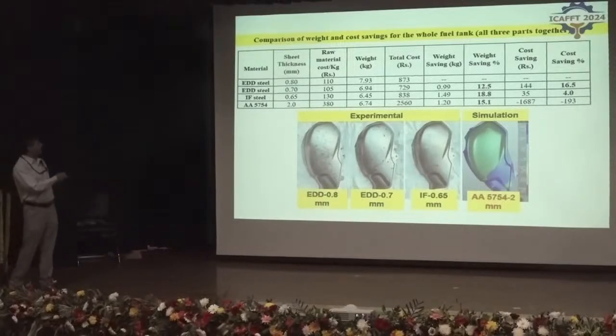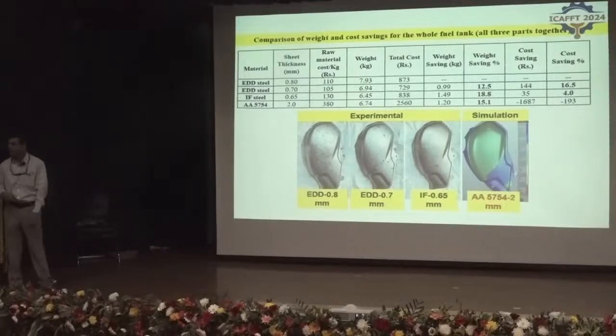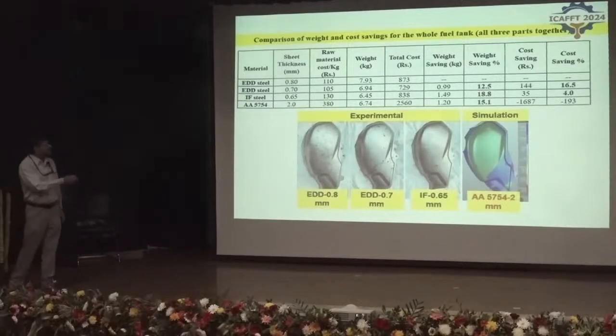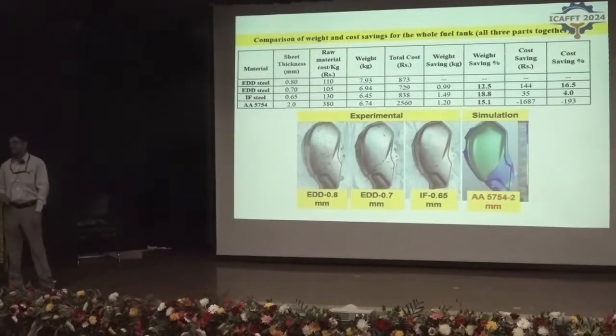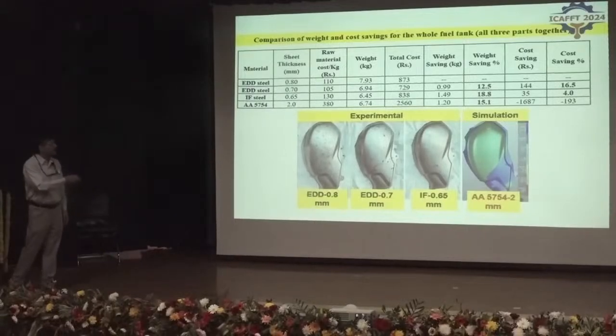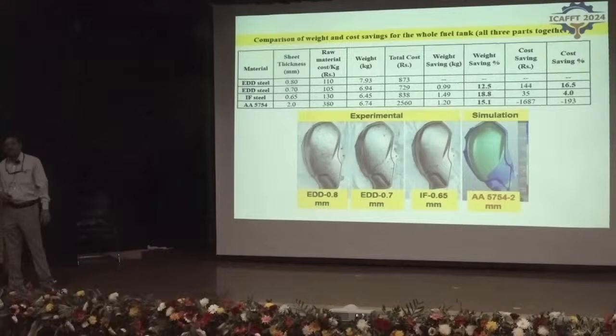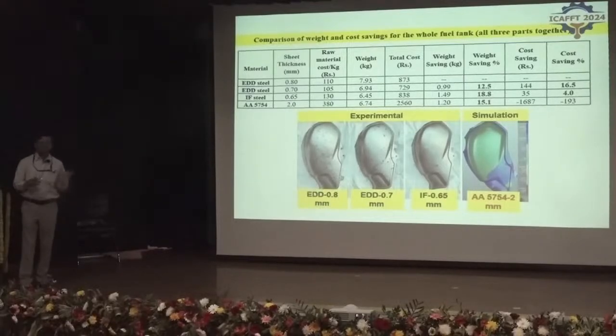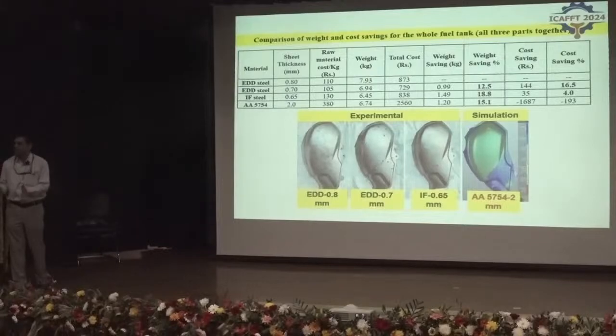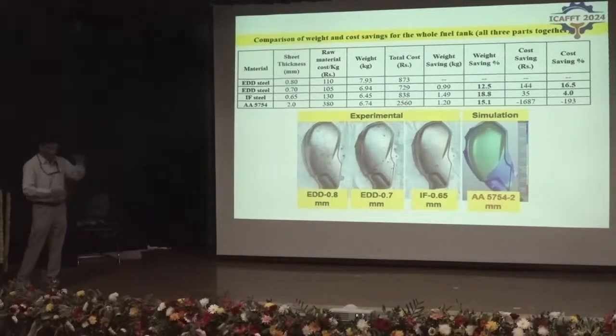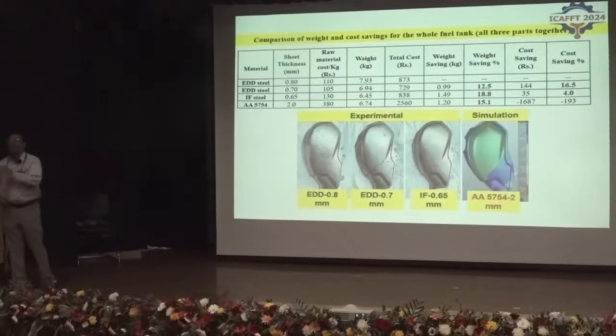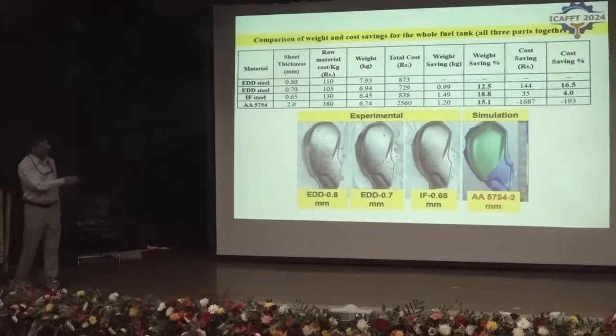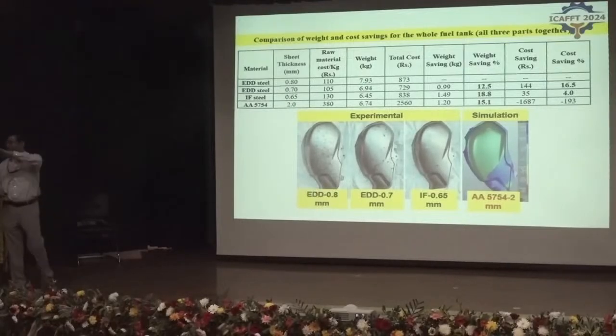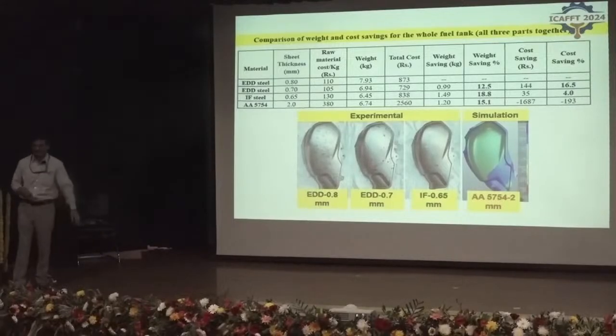And if we completely change the material to aluminum, we need to increase the sheet thickness to 2 mm to prevent any failure. But in such a case, we would get a weight saving of 15%. So if you look at the cost, it is highly negative in case of aluminum. But what we expect is that if this kind of simulation methodology is followed for various other components, and if we can reduce the weight significantly, in the long run, the improvement in the fuel economy would actually offset the cost saving. I mean, it would offset this negative cost saving. Okay.